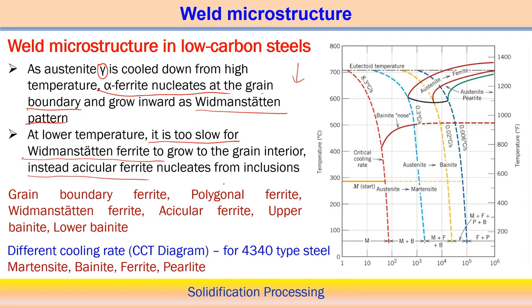And if you analyze low carbon steel, these are the different types of microstructure that usually form: grain boundary ferrite, polygonal ferrite, Widmanstatten ferrite, acicular ferrite, then upper bainite and lower bainite structure. All these different phases or structures are usually formed in low carbon steel, and all depend on the temperature gradient, how the solidification occurs, how the grain growth occurs, and what cooling rate is followed.